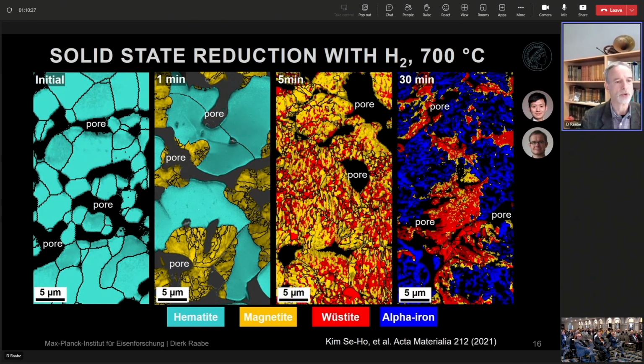And of course, always associated with an ongoing further massive loss of mass, namely of the oxygen, which is then creating, of course, nanoporosity. And then the last stage is this very sluggish one from the wüstite into the alpha iron, as you can see here. Always with still encapsulated and closed and maintained wüstite in the center. So you have always gradients in the material.